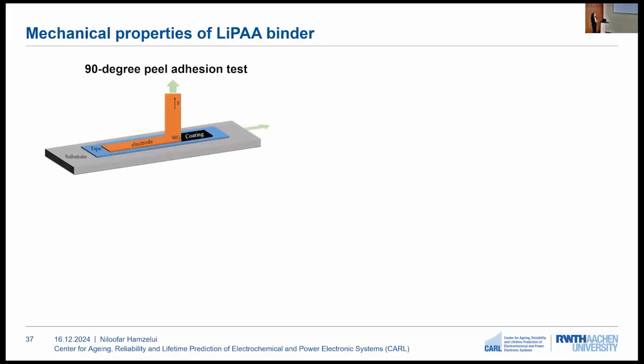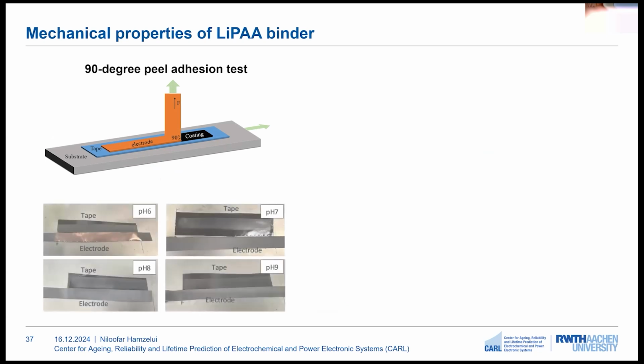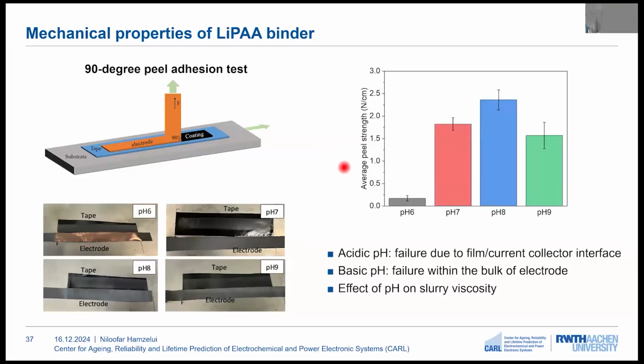These LiPAA binders were used in the electrode, and the mechanical property of the electrode was investigated using a 90-degree adhesion peel test. Here we can see the electrodes after the adhesion test, and here we can see the average peel strength at different pH. It can be observed that for pH 6, we are having a lower peel strength, and as it can also be observed here, we can see that the whole electrode is stuck to the tape after the measurement. So this can indicate that the failure here is due to the film current collector interface.